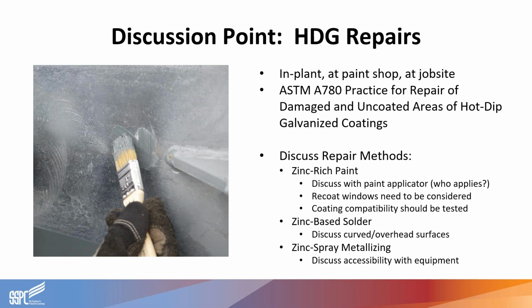But if the galvanizer intends on using a zinc-rich paint for repairs that are conducted at the galvanizing plant, the recoat time windows really should be evaluated by the specifier, because practically, in terms of logistics, you may not be meeting those recoat windows by the time it gets to the paint booth. Depending on the compatibility of any zinc-rich paint with the paint or powder coating that's going to be applied overward, that also should be discussed directly with the paint manufacturer to check that compatibility. That's important to consider because, from galvanizer to galvanizer, the zinc-rich paint products that are available can vary quite a bit.